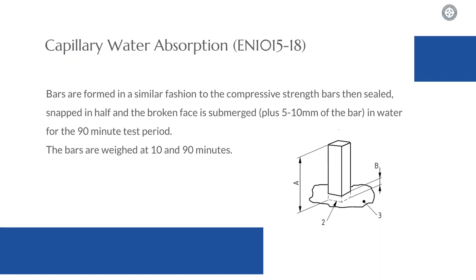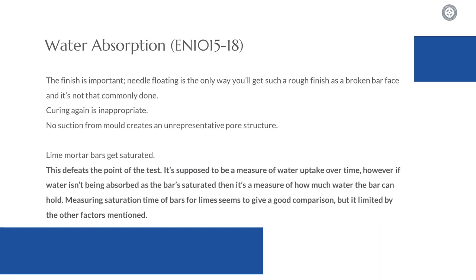Going on to water absorption: you form the bars in pretty much the same way, you snap them in half, you take the broken face and submerge it in water, and you test this for a 90-minute period to see how much is absorbed. These bars are weighed at 10 and 90 minutes. Again, you have the issue of no suction from the bar mould creating an unrepresentative pore structure. The biggest problem with this test when you're dealing with lime mortars is that the majority of the time the test actually fails — you wind up with a saturated bar. If you're supposed to be measuring water absorption over time but your bar gets to the point where it can't absorb water because there's no space left, then you're not actually measuring water absorption over time anymore.